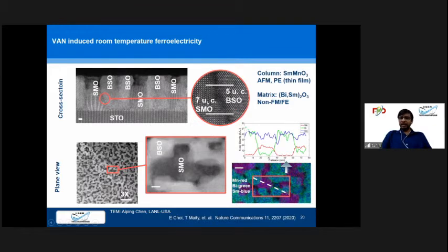And here, if we can see, this is the out-of-plane or z-axis crystal structure matching. When you grow in the upward direction, 7 unit cells of samarium manganese oxide match with 5 unit cells of bismuth samarium oxide. So this one is creating in-plane strain, in the A and B directions, and this is creating out-of-plane strain in the C direction or Z direction.